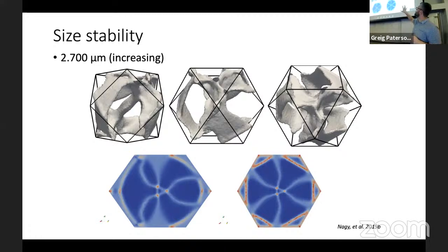And you can see that those regions, I guess you have to take my word for it, correspond to the gaps in the regions in the top images. They correspond to the domains that we see in the grain. As we begin to decrease the size of the grain, what we find is that the structure actually remains. It's stable, and so there's hysteresis there in the structure because it's not disappearing.